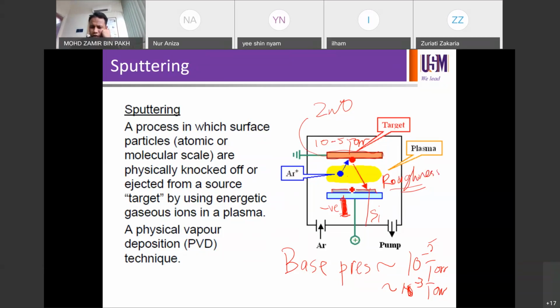Roughness because of more bombardment of your plasma on the silicon surface. So while having deposition, you are actually doing etching to the substrate. So this is what we did last time when we tried to develop ITO thin film, or in fact more than that, on glass and aluminium on a sputtering chamber at Fuji Electric.